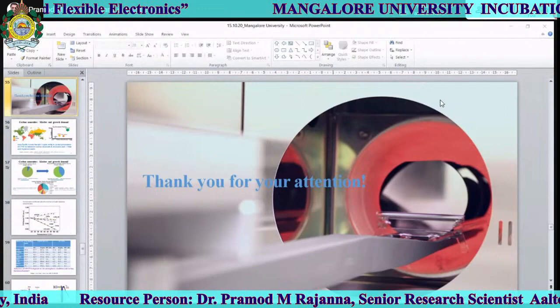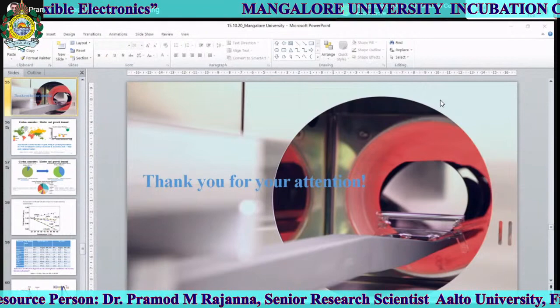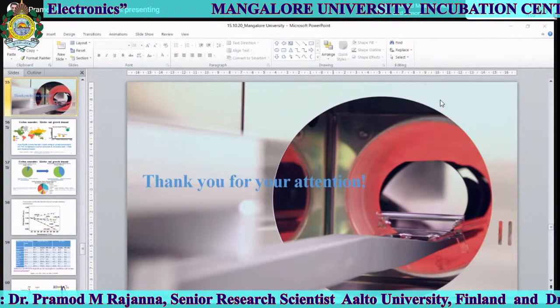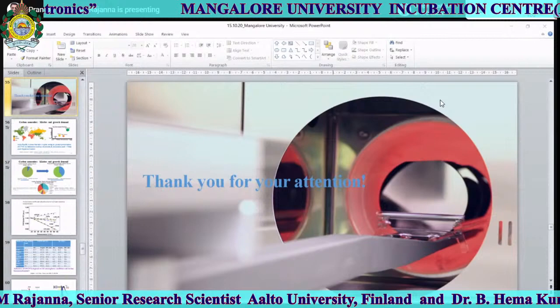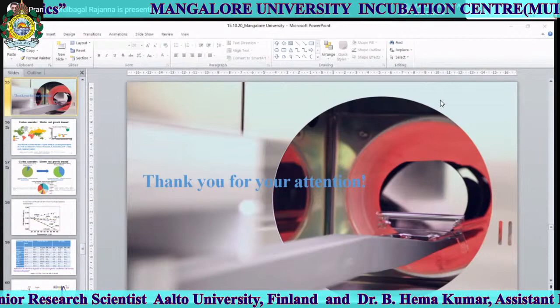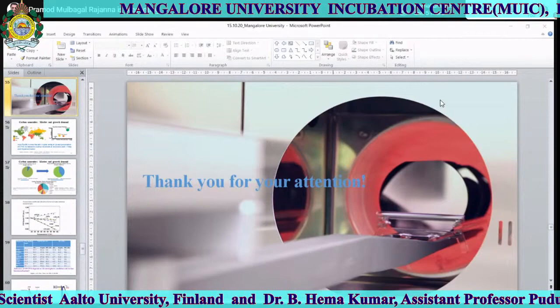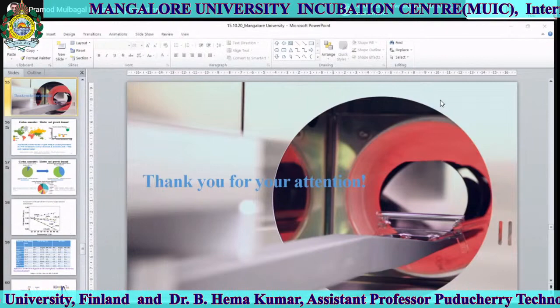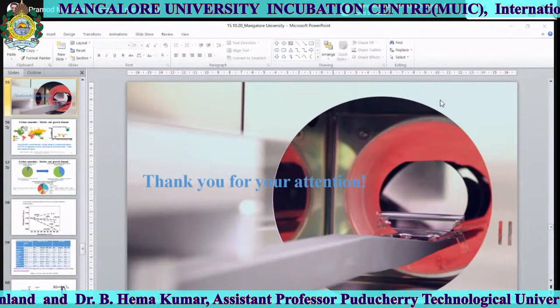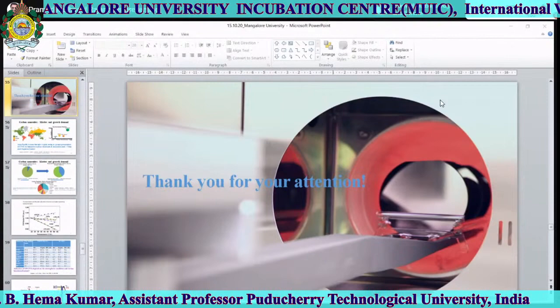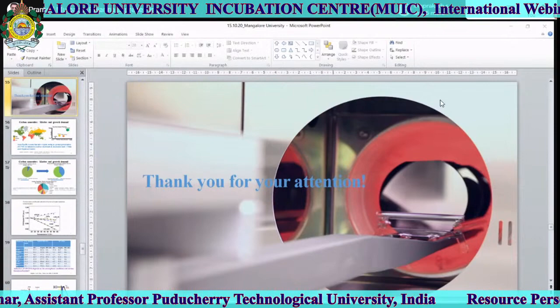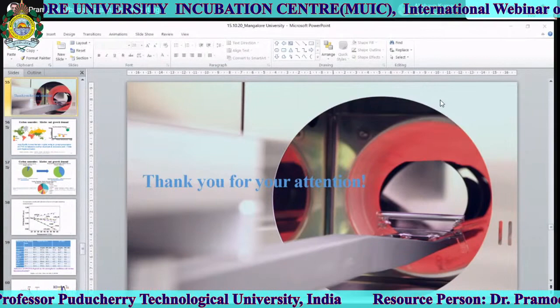Is it possible to enhance the efficiency of single wall carbon nanotubes for solar cell and storage applications? Yes, it is possible. In energy storage devices, you mainly use it as an electrode, so what matters is not the optical properties but the electrical properties. What can be done is chemical doping, as I showed in my work. We use chloroauric acid, which is a wet chemical doping. There are other approaches too, like in situ doping during the synthesis of the material. Unlike silicon, where you have substitutional and interstitial doping, here all the carbon atoms are on the surface, and when you dope it there is an intermolecular interaction by which there is electron transfer.